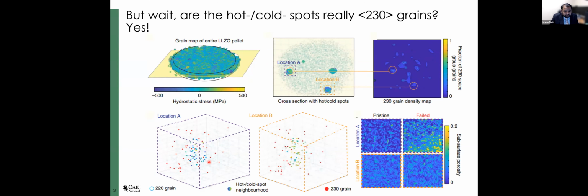And so if you see the spatial mapping here, you can see that the grains identified in this blue yellow scheme are the grains from the hotspot and the cold spot, while the grains identified as red here are the 230 space group grains. So we essentially were able to show that the hotspots and the cold spots and the 230 space group grains are highly co-located within the entire bulk. And if you look at the subsurface porosity at these different locations, we also show that these regions were the ones that show very large changes in porosity, consistent with what we observed before.